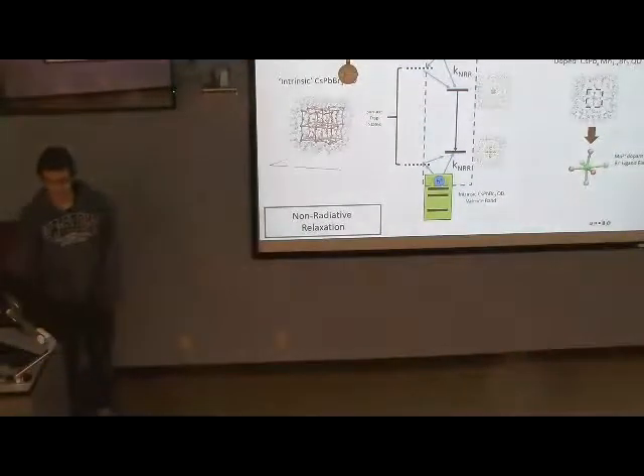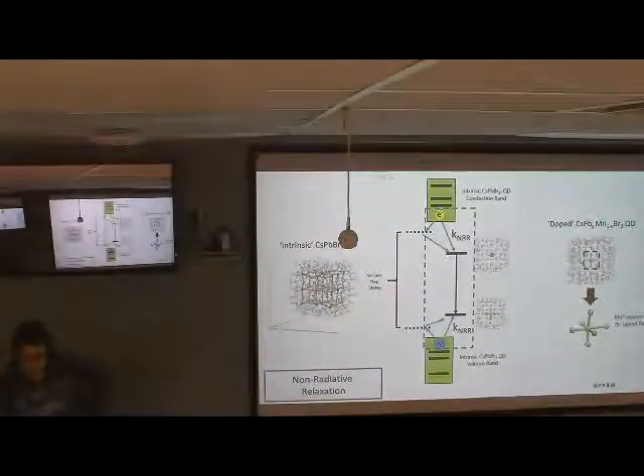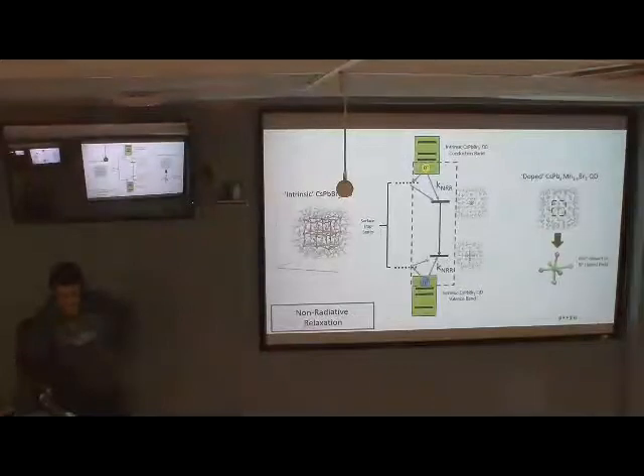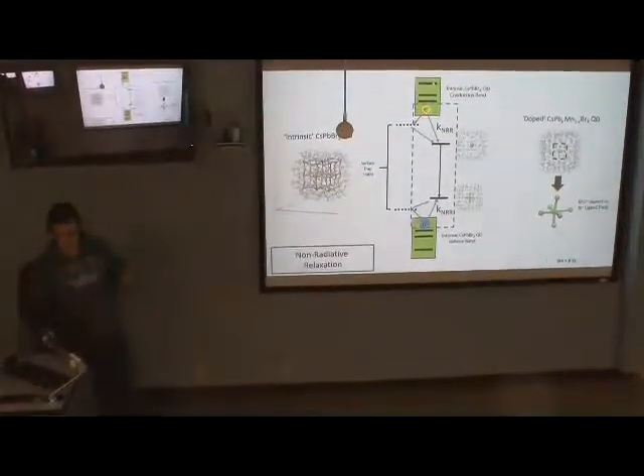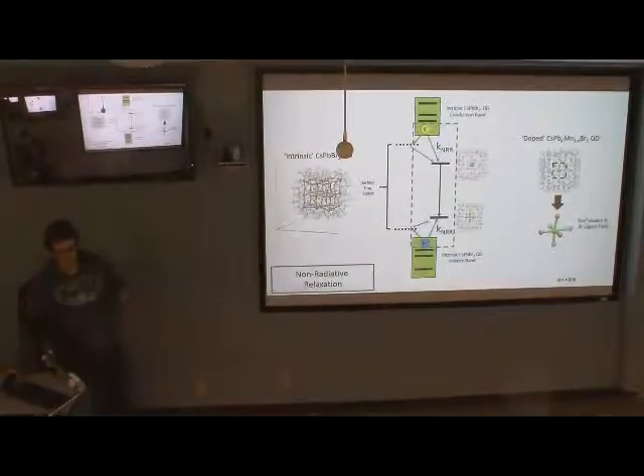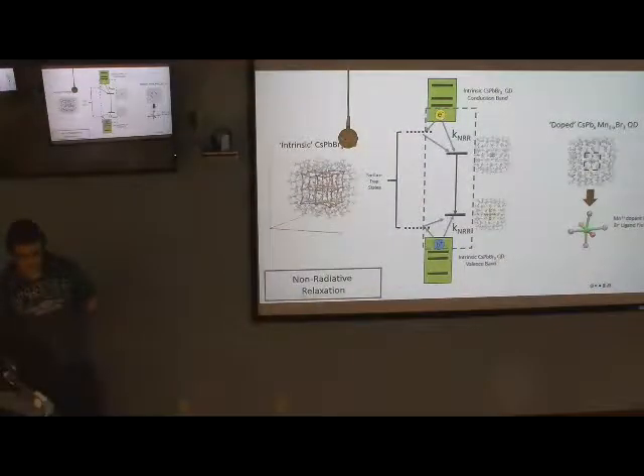So yeah, non-radiative relaxation. The way that can be modeled is the perovskite is still going to be the absorber, so the excitation is going to be on the perovskite, and it's going to relax to the band edges of the perovskite. And then from the perovskite, the electron and hole can relax to the dopant states inside the gap, and it's going to happen at some rate. Ideally you'd like them to be at the same rate, because otherwise you'll have a hole waiting for the electron, and where it could be emitting, it wouldn't. So ideally you'd like both rates to reach the manganese states at the same time.